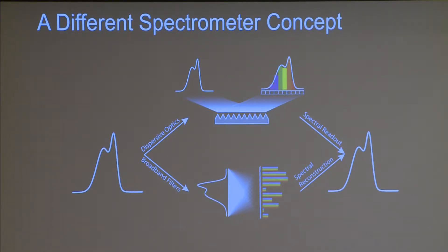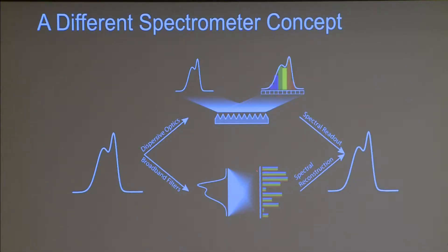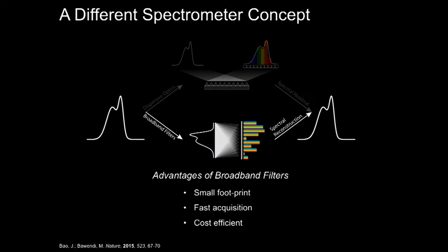You can do this with quantum dots in a scalable way, because you need a very large number of ways of changing the spectrum of the object — say 200 different absorption spectra that you want to be able to print. You want to print little spots of 200 different kinds of quantum dots to recreate your object. The advantage is that you eliminate the moving parts of a spectrometer, eliminate the grating and all these things, and now your spectrometer fits right on the imaging chip itself — which could be like an iPhone camera chip — a very small footprint, with video-rate acquisition and very cost-efficient.